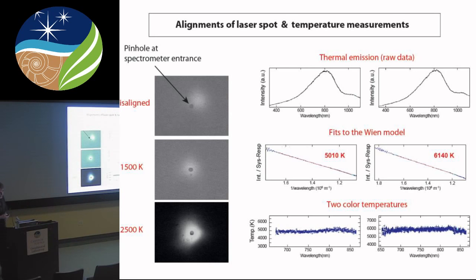These are some temperature measurements I show for extremely high temperature, like 5,000 or 6,000 K. This is the raw data. We correct the raw data with the transfer function from the experimental setup, and we get those fits. And this is the two-color fit, which uses a pixel or region one by one, showing that the pattern is extremely good. This is regular, meaning thanks to those reflective objectives, changing from one cell to another makes basically the same fit extremely well. As soon as you have enough intensity, of course, on a different part of the pattern, then you get an extremely nice fit on the range of energy of the wavelength here that is relatively comfortable. So we're relatively comfortable with that.